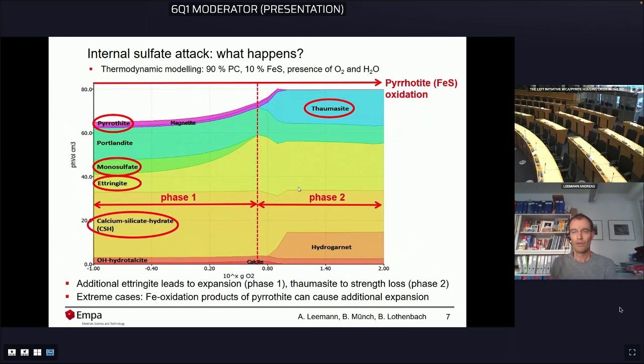So don't be afraid, it's not as complicated as it looks. So what do we have here? This is an image that was done with thermodynamic modeling. Now, what you have are the hydrates formed by cement hydration. So this is what is present in your concrete. Now let's start on the left-hand side. At the bottom, I just highlighted the phases that are important to explain what happens. So first, you have the calcium silicate hydrate, abbreviated CSH. You have ettringite, you have monosulfate.